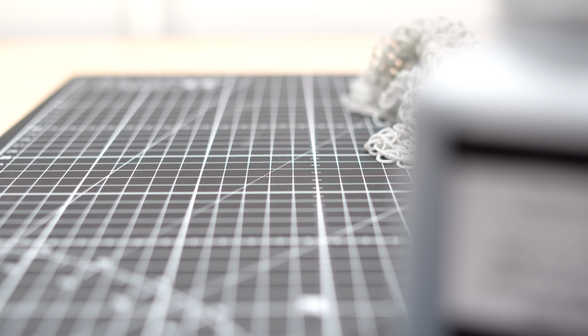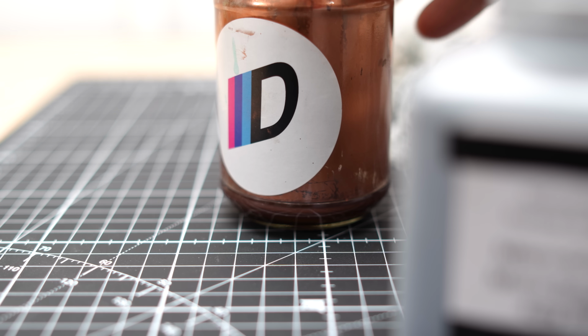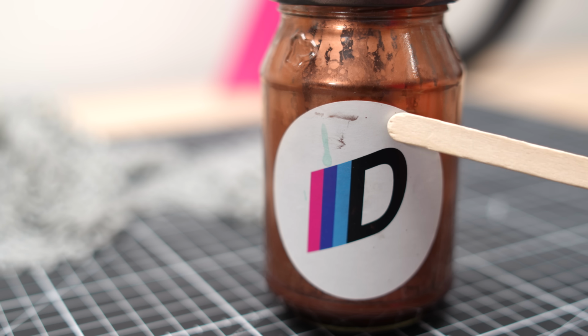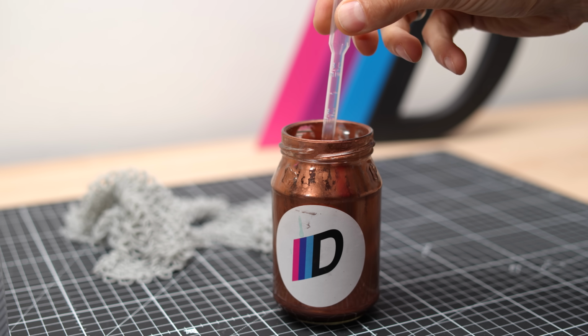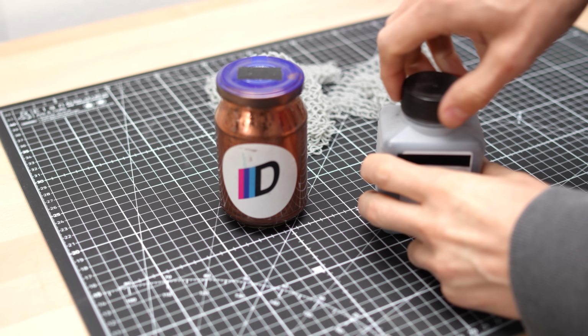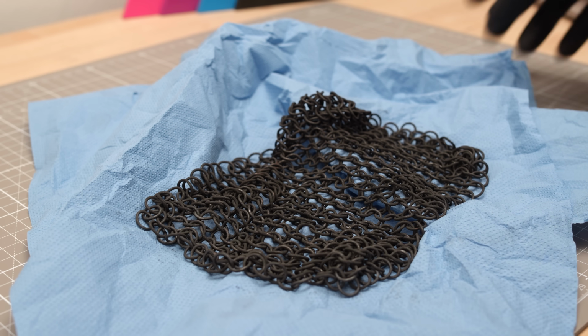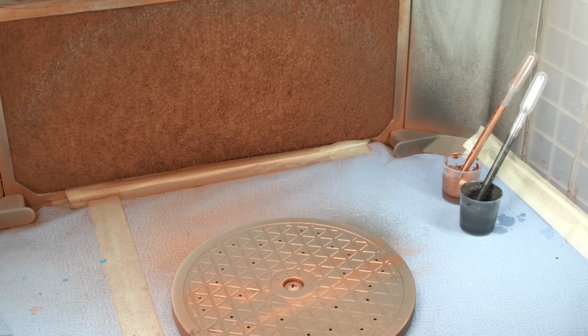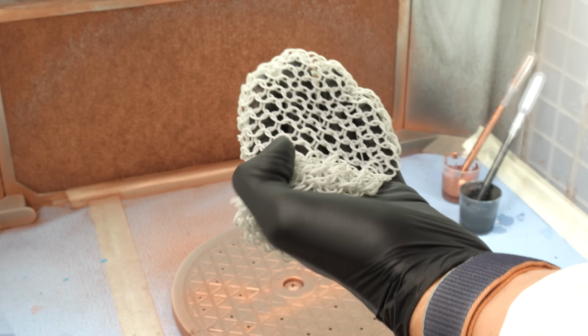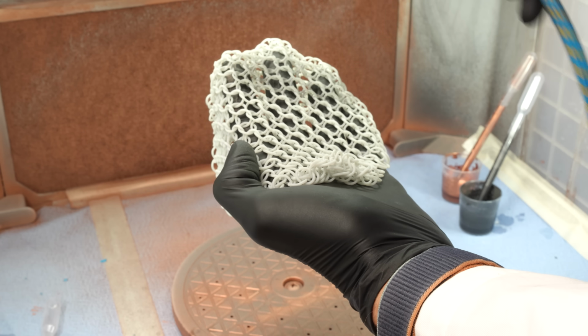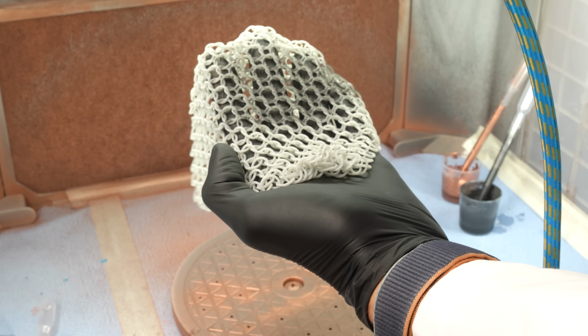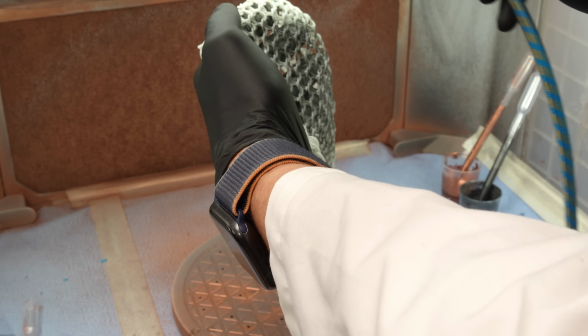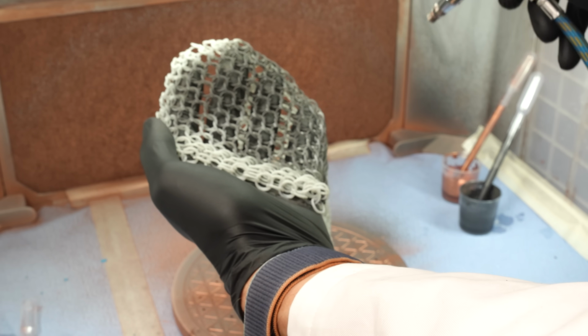Alright, so I use two types of conductive paint, copper conductive paint and graphite paint. Both work well, but the copper one goes on more evenly and has better conductivity. The graphite paint, on the other hand, is super durable, but after spraying, it needs a little extra work to make it really conductive. I'll get to that in a bit. Also, with the right kind of graphite, you can actually make tons of it yourself for super cheap. The tricky part with flexible prints is making sure all the little segments are conductive and that they are all touching in the plating bath so the current can flow through everything.